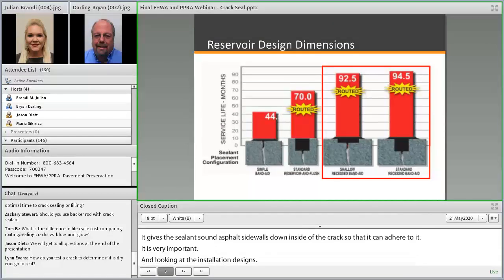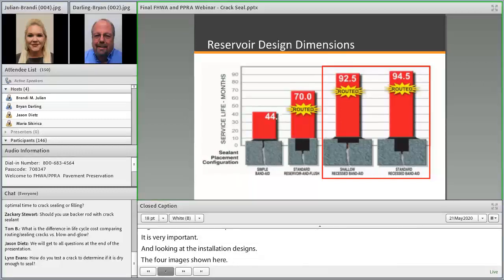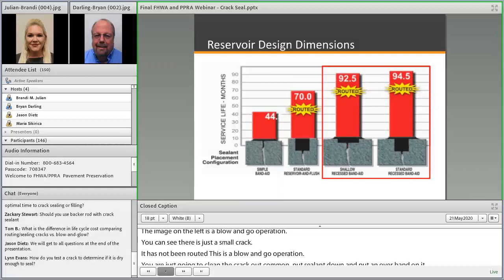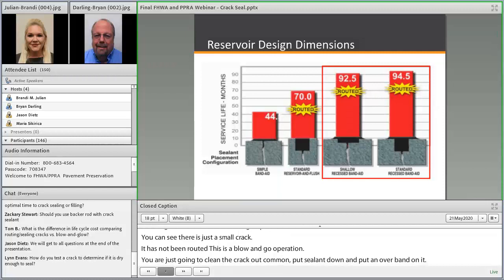And looking at some installation designs, the four images shown here, we're going to start left and move to the right. The image on the left is a blow and go operation. You can see there is just a small crack and has not been routed. So this is a blow and go operation. You're just going to clean this crack out, come in, put some sealant down, and put an overband on it. With this operation, we typically see approximately 44 months of sealant service life.